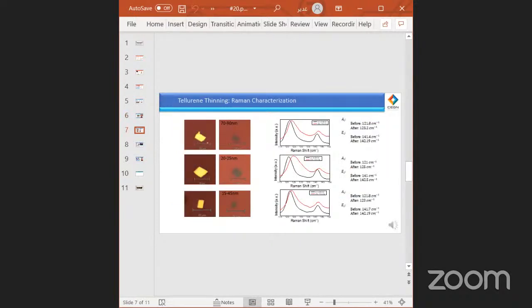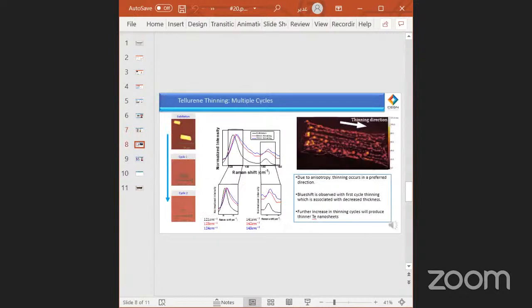Here we show some of the Te flakes that have the same effect after annealing. All the flakes show a color change, a drop in thickness, and a blue shift in Raman spectra, where the first sample has almost a shift by two, both in the A1 mode and the E2 mode. And the second sample shows a drastic thinning where it has a shift by four. The same also happened in the third graph. This behavior happened for all our samples, and the change in the thickness varies depending on the annealing time and temperature. In this slide, I want to mention that Te can be thinned in multiple cycles.